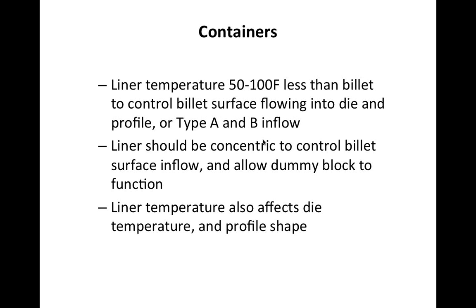The liner temperature also affects the die. If we use containers with external heating, typically the top of the container will be anywhere from 50 to 100 degrees hotter than the bottom of the container. This is because heat is being leached out of the bottom of the container into the container housing, and heat is rising within the container and the container housing, making the top of the container hotter than the bottom. If this is the case, once you have conduction between the liner seal face and the die, the top of the die will become hotter than the bottom of the die. The flow stress of the alloy at the top of the profile versus the bottom of the profile will be less, and we'll have more flow, which is going to cause us inconsistent shape and also wall thickness.